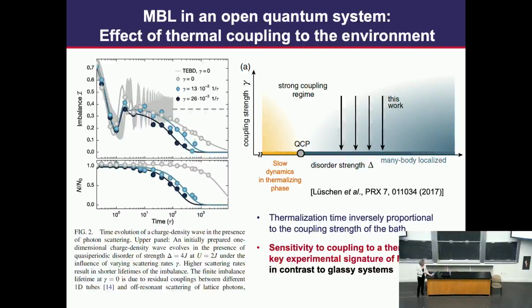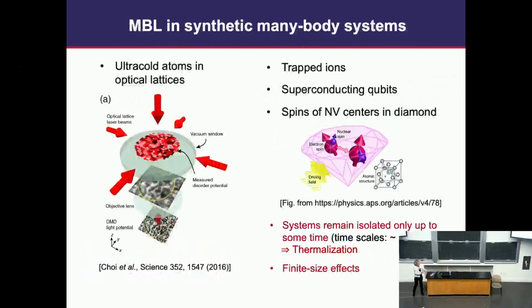So we're limited, or they're limited, by time scales. Typically the largest thermalization time is a millisecond, so you need to use experimental probes that can probe shorter time scales. But also these systems are relatively small - the largest one has maybe 10,000 atoms, but typically they're smaller.